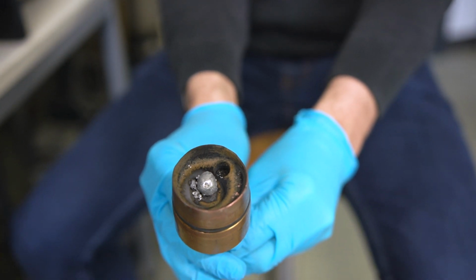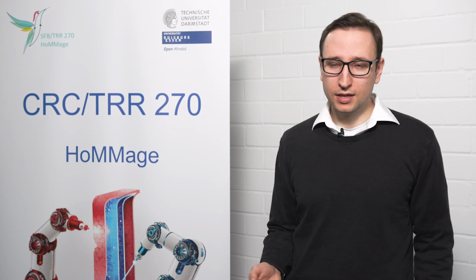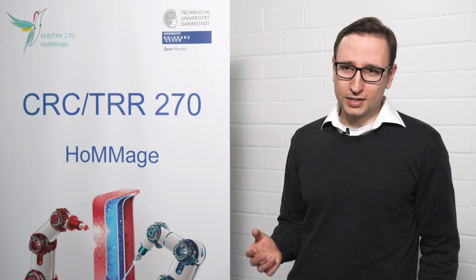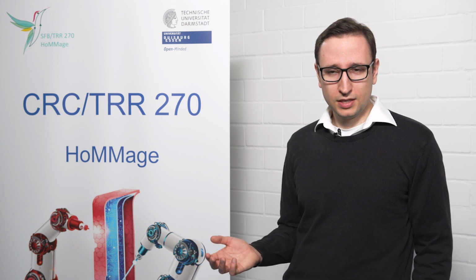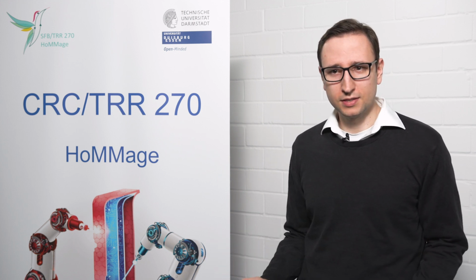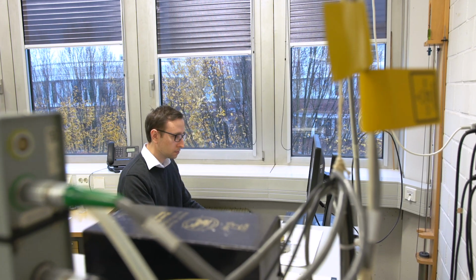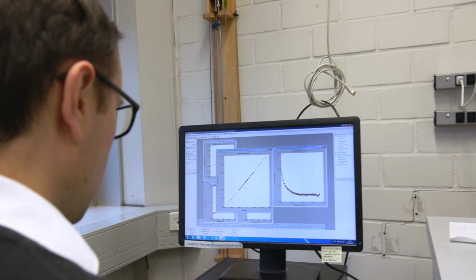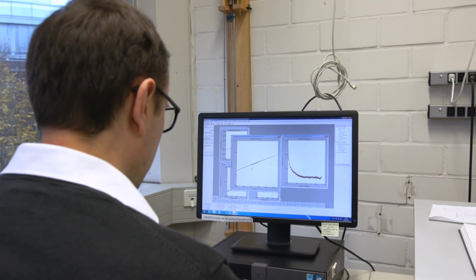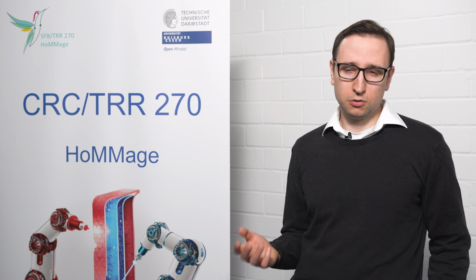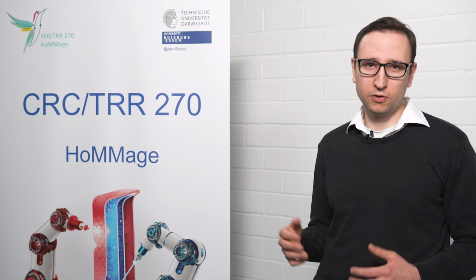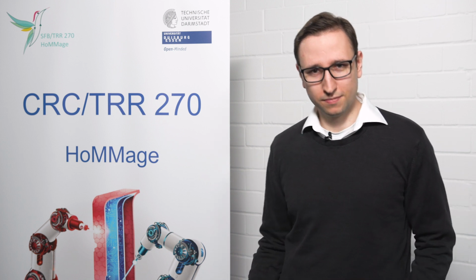This is done in a superconducting quantum interference device, in short, SQUID. It can measure the magnetic field-dependent magnetization of a sample in fields up to 5 Tesla. The data is then analyzed, and the results are used to optimize the material composition and treatment further. The final goal is a new generation of permanent magnets with a preferably small ecological footprint.